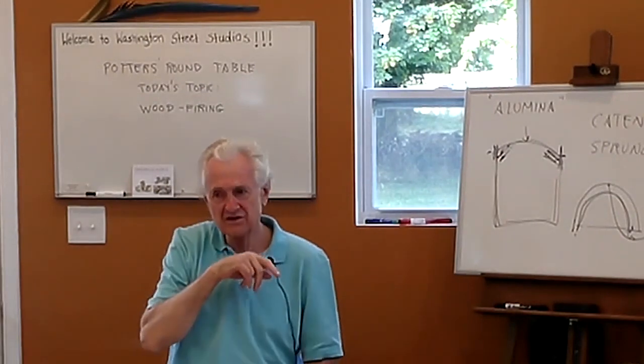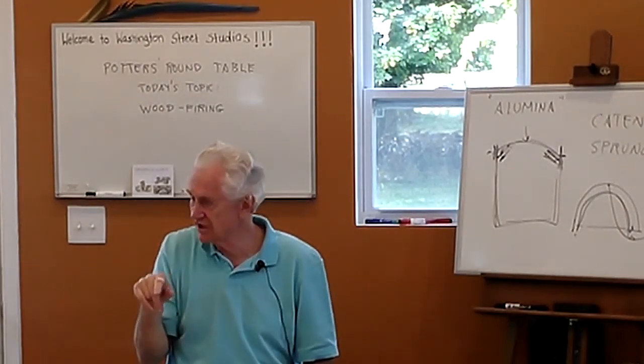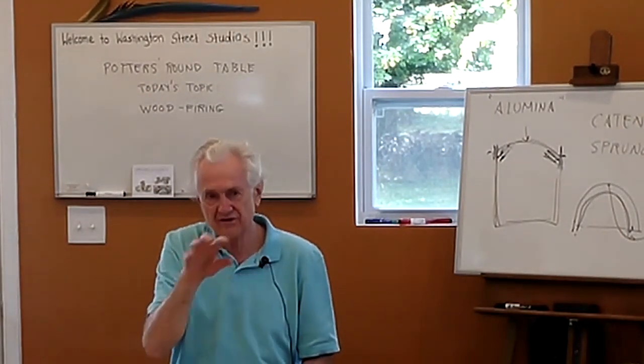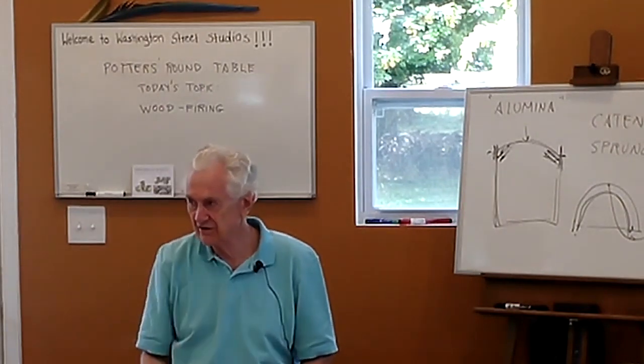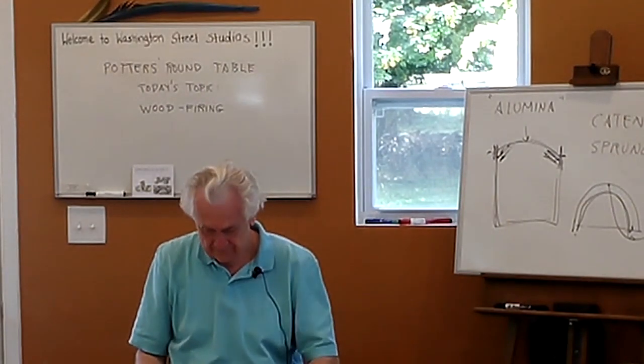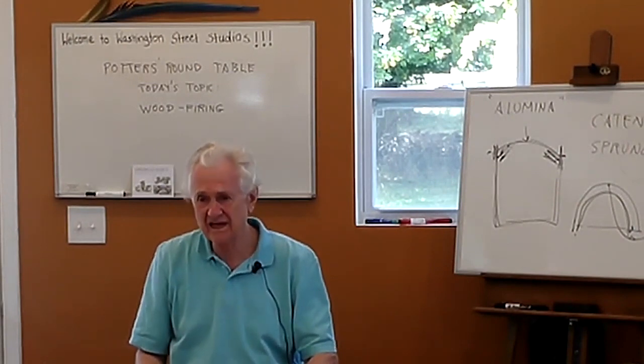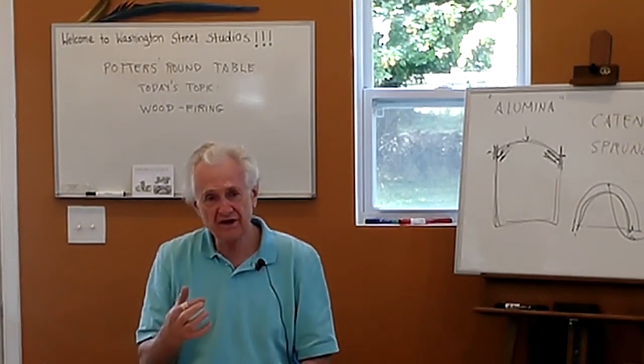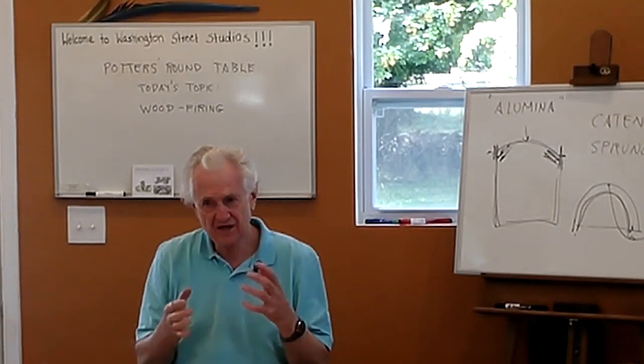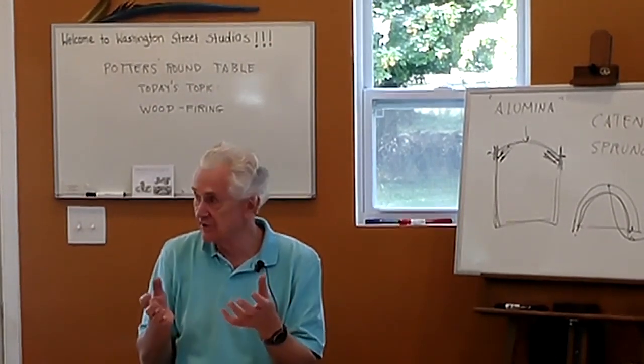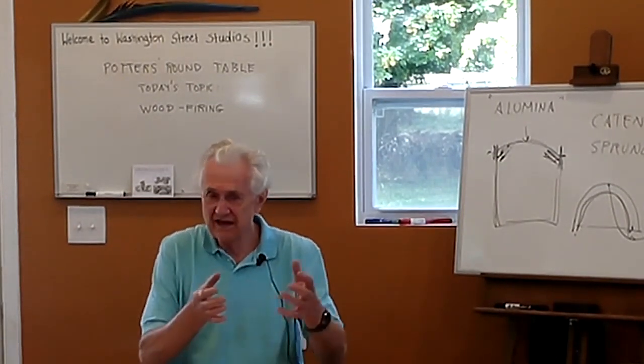So you're not even usually heating in a constant state of reduction or oxidation. It's alternating. It's going heavy, light, heavy, light, heavy, light, depending on as you stoke. So you sort of get a wavy heat rise. Because when you're burning the fuel inefficiently, when you're not burning it completely and you're in heavy reduction, then you're not getting the most heat out of it.